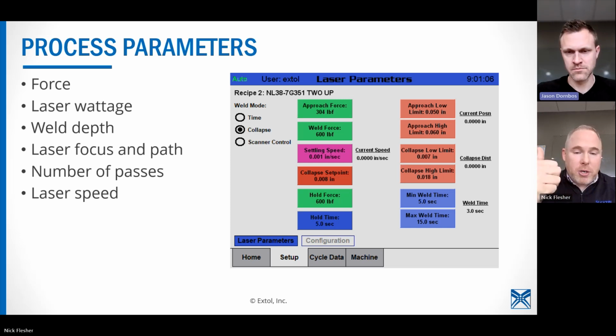How much wattage you're using, which I'll show here in a moment, of how we control that. You can see those limits, approach limits, to make sure parts are loaded correctly. Lower and high collapse limits, those are our main quality parameters, as I mentioned, if you weld to collapse. And then you can overlay time on that so after you get enough data to say, I'm within my process control for that. You can also go by number of passes, and you can adjust speed.